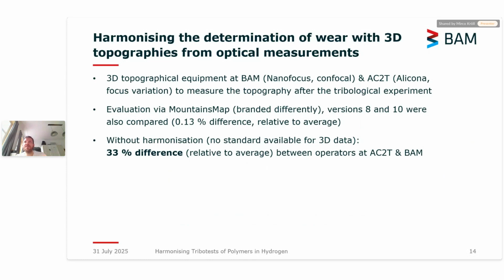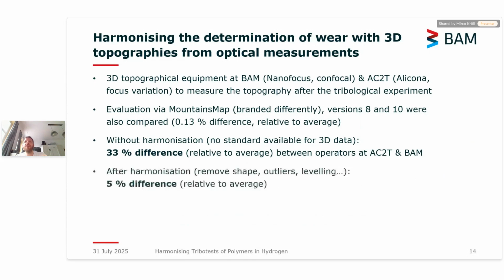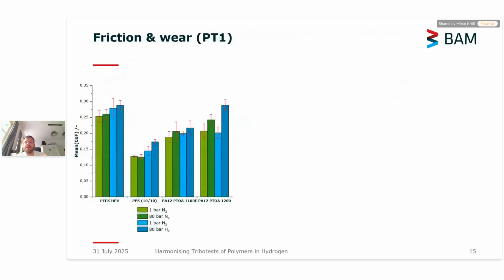So we saw, okay, this is an issue. We need to harmonize how AC2T and BAM are doing things. And if you do that, for example, how to remove the shape, remove outliers, and level the topography, we were able to reduce that to a 5% difference, which is not perfect, but much better than 33%. So harmonizing actually helps to make results comparable.